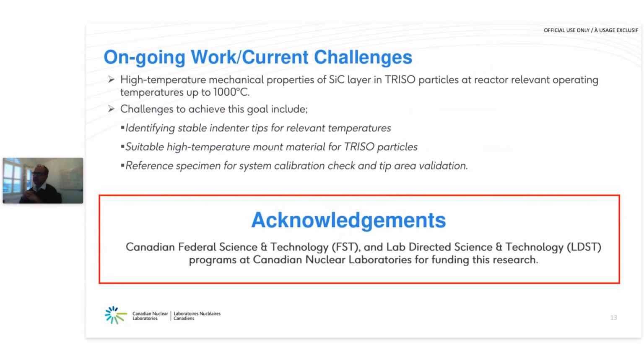The ongoing work and the current challenges, as I was explaining earlier: the intention is to measure the properties of the silicon carbide coatings at relevant temperatures up to 1000 degrees C, and the challenges are very well laid out by Professor Janet. First is to find stable indenter tips to go to these extremely high temperatures. The second is finding a suitable high temperature mount material for TRISO particles.